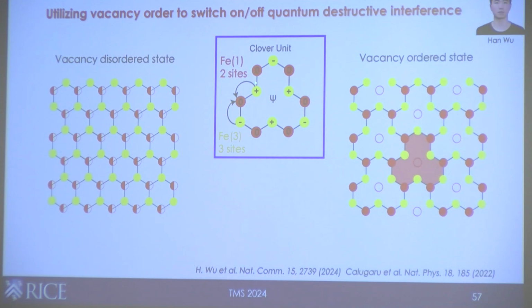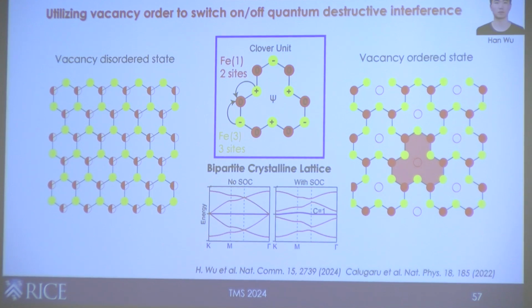So if you count up in this unit cell, the red site has 2 per unit cell, and then the yellow site has 3. And immediately, as we learn from Dmitry and Nicola and collaborators here, this kind of a bipartite lattice would guarantee that you have a zero mode or a flat band. This is what you would get from a tight binding calculation with the nearest neighbor hopping for this lattice.